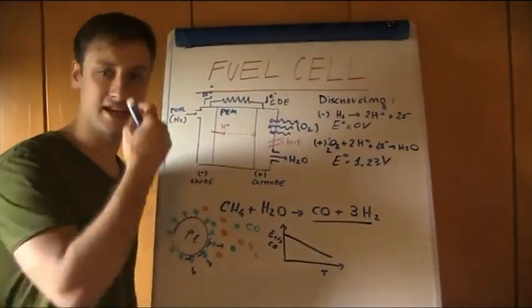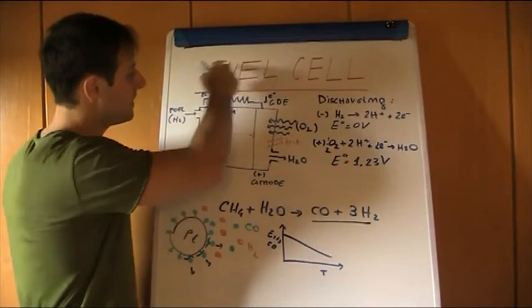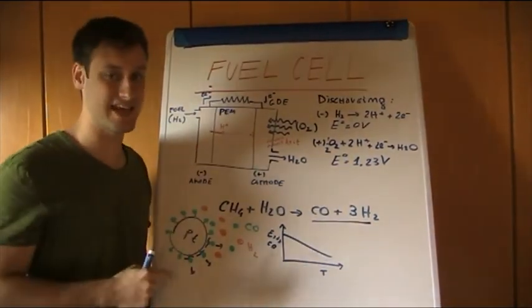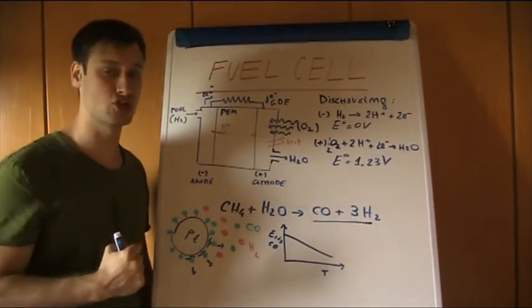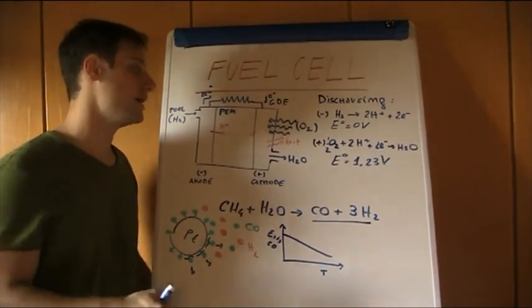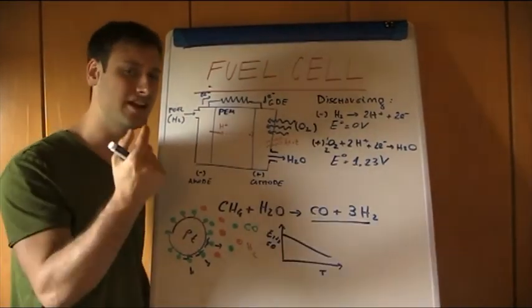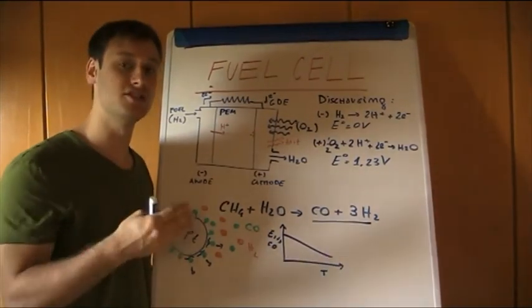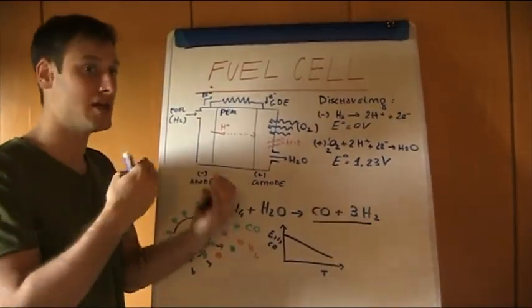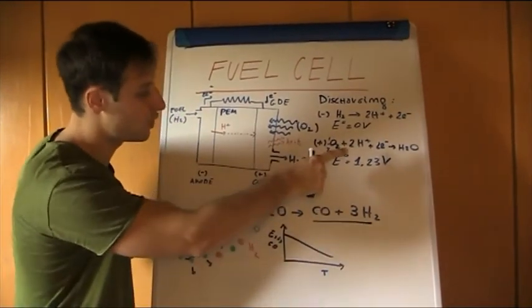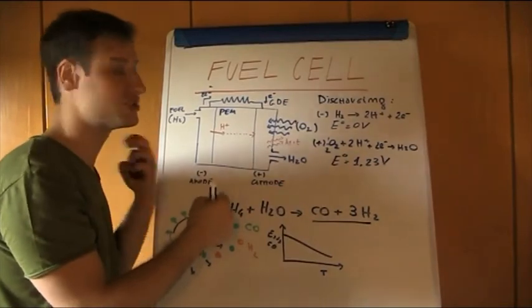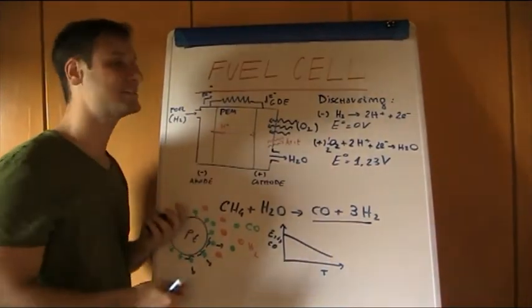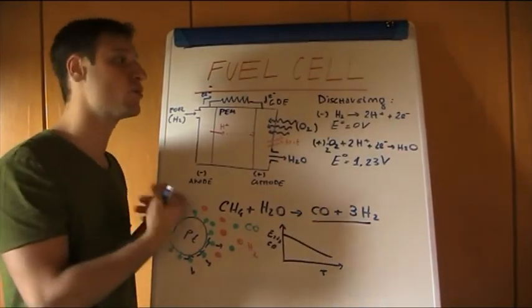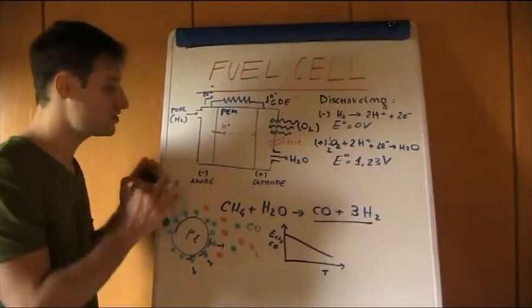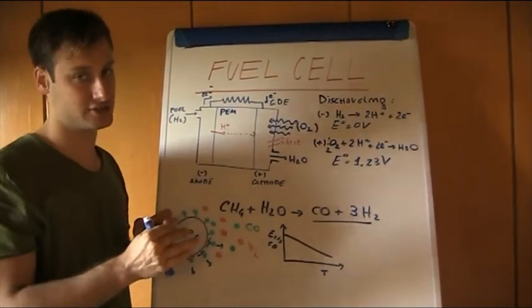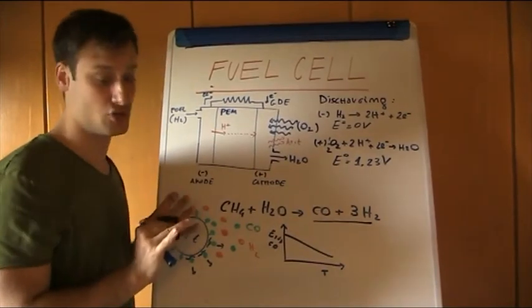And so it's important to say that in these types of fuel cell, the ones based on a proton exchange membrane in a wetted state, we need to be aware of the temperature, the working conditions, and the management of water, including a quantity of binder Teflon really tuned inside the gas diffusion electrode. In this way we need the right compromise between the right hydrophobicity in order to avoid flooding, and at the same time ensuring that the water inside the membrane remains present without undergoing evaporation and drying. So this is just a matter of water management, that should be completely tuned in the best way.